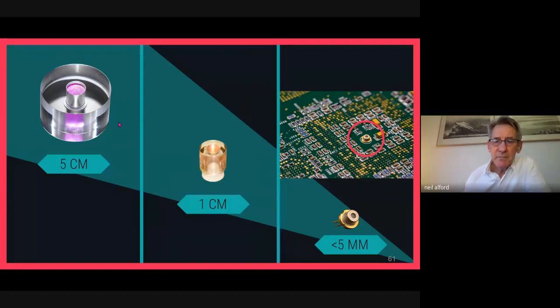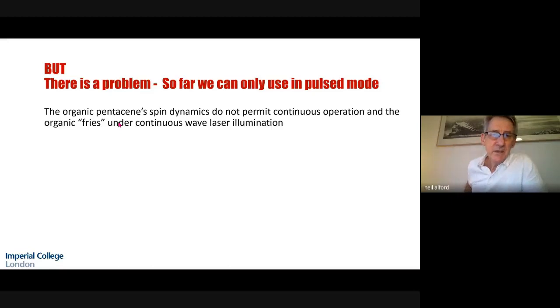So we were able to miniaturize this quite well, but there's a problem. We can't use it in continuous mode because the organic pentacene, first of all, the spin dynamics do not permit continuous operation, and the organic simply fries under the continuous wave illumination.